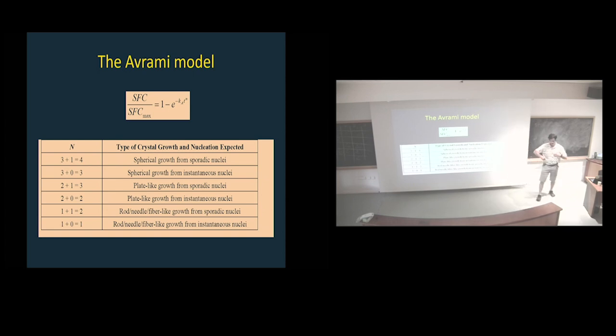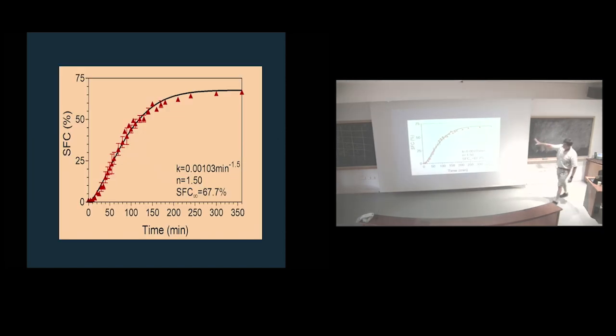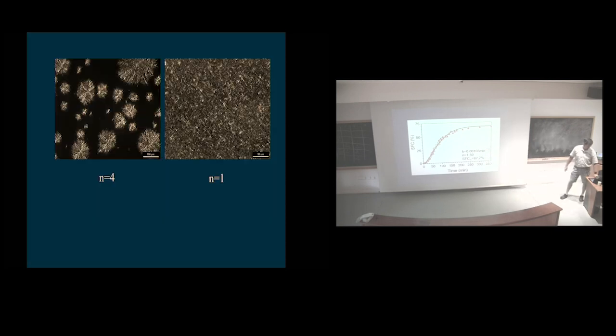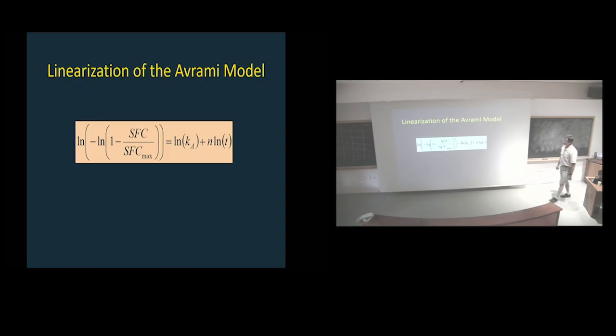And then there's papers and people justifying why it's 2.3 and not 2, but I don't care. I have my index of crystallization. And so it fits the data fairly well. And so you have, this is just the SFC measurement, and you can derive from this an n and a k. That gives you at least a measure of crystallization speed. Very different. If that's analyzed and has an n equals 1, n equals 4, at least you can look at it and say maybe that's how it was.